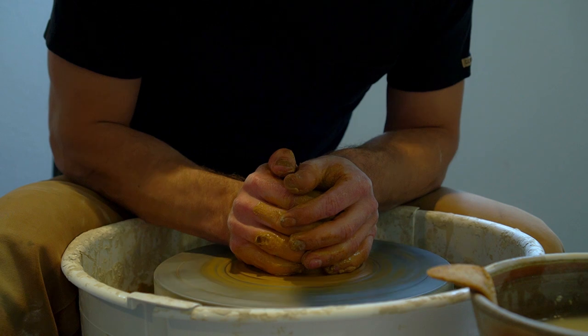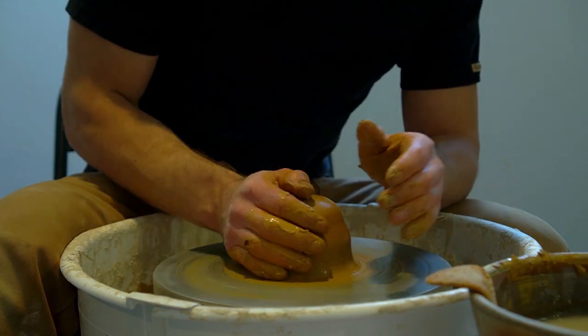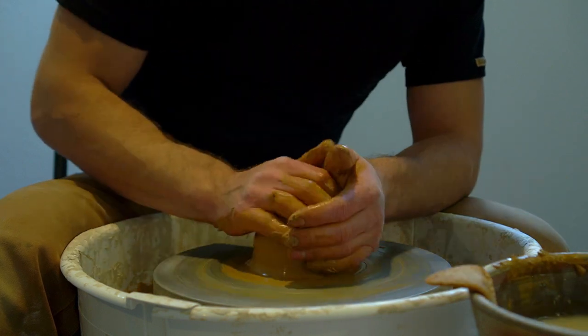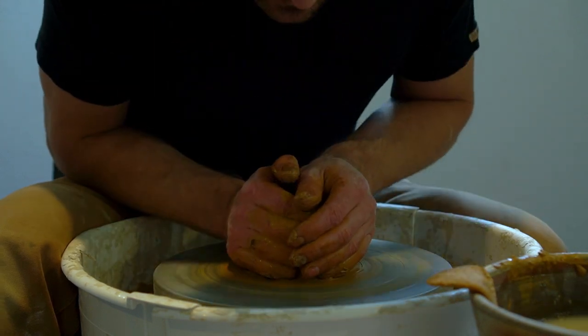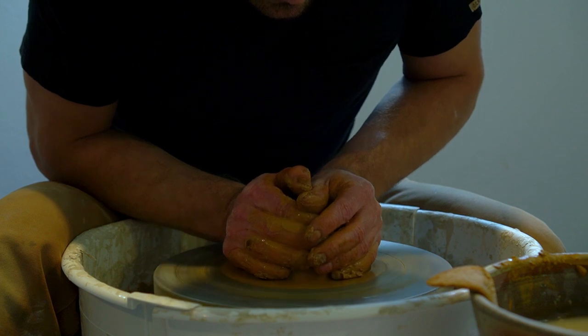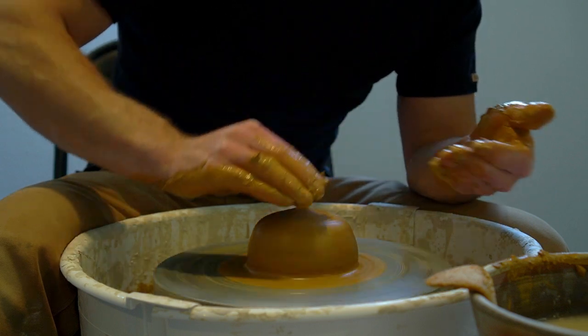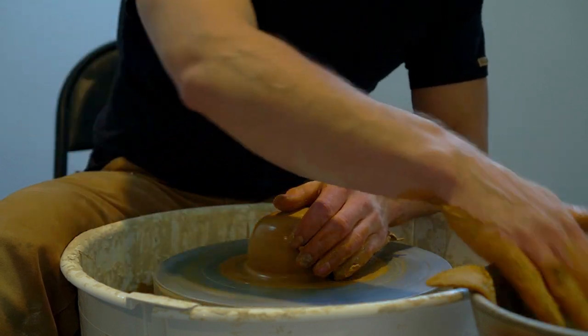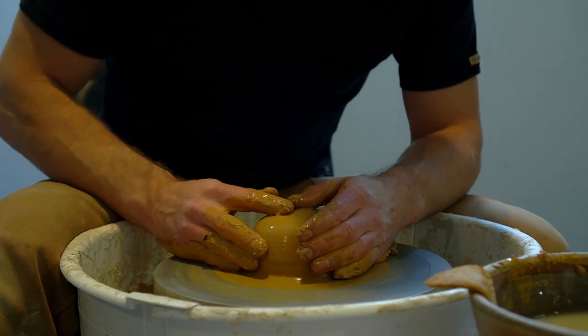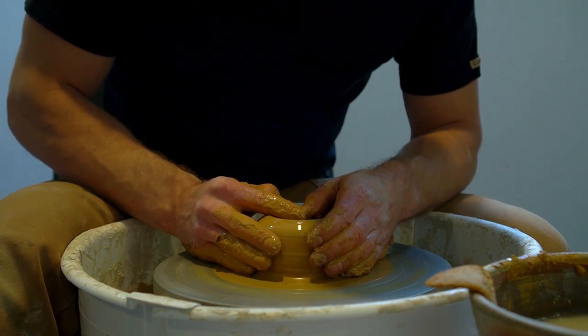But honestly, I find that this wild clay has much better structure than porcelain. When it's the right consistency, it feels like it would be harder to mess up than to make a thin-walled pot. And unlike pure white porcelain, it's this gorgeous orange color. When it's fired, it'll turn red. And the hotter it's fired, the darker it gets — passing through bright red at cone 6, toasty brick red a little hotter, all the way to dark brown at cone 10.